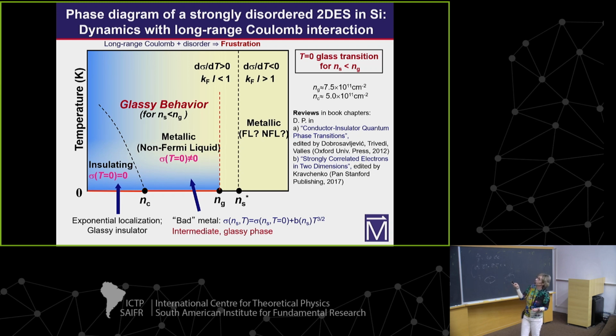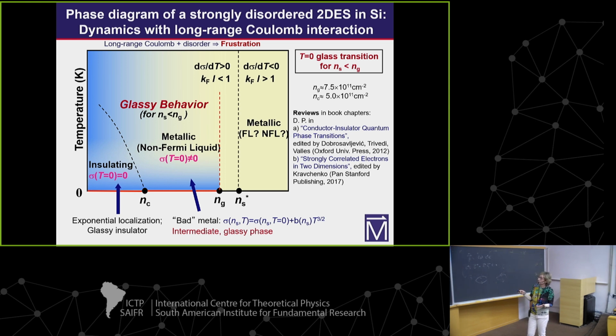Here, this is just a sketch which shows where we observe this glassy behavior. The onset of that is here. There is a well-defined density below which we observe glassy dynamics, and this is exactly the beginning of this bad metal regime. So we have, between an insulator and something else, in the regime when k_F l is greater than 1, this intermediate bad metal glassy phase.